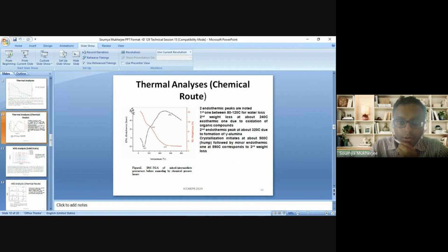In the case of the chemical route process, which is carried out with the help of fuel, we have observed initiation of crystallization around 500, a minor exothermic hump. To get the proper phase, we have increased the heat treatment schedule, actually the heat treatment temperature. In the intermediates, we are also getting some gamma alumina formation, which is obviously not our interest, but we still get it since we want to develop the spinel.